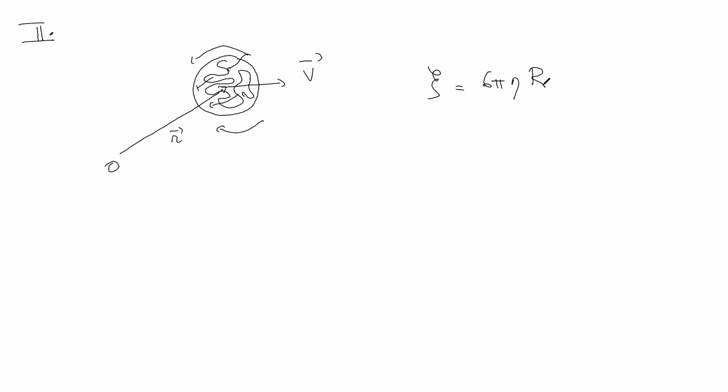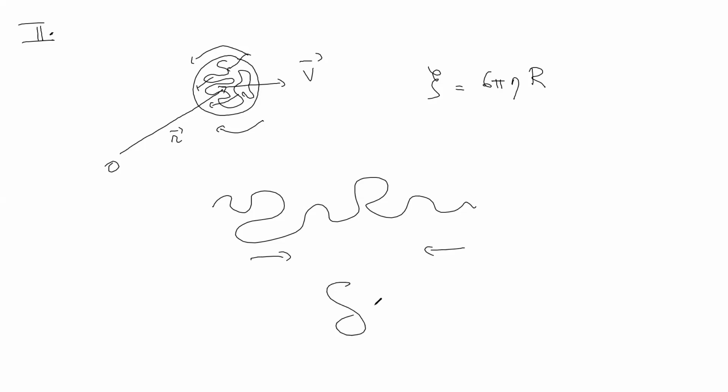But in fact, the polymer chain could experience some elongation. We know that you can pull on it, for instance. So due to fluid flow, due to fluctuations, whatever, you can have some stretch-like object and not coil-like object. Therefore, in this description, we are neglecting the inner degrees of freedom. Okay, and so in fact, there is a time scale associated to the relaxation of that polymer chain toward a more typical configuration, where you have a lot of microscopic states corresponding to it.